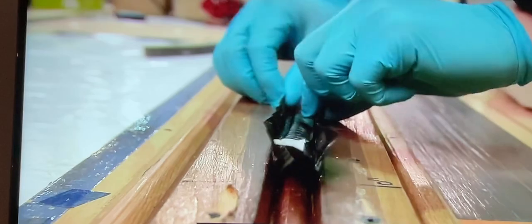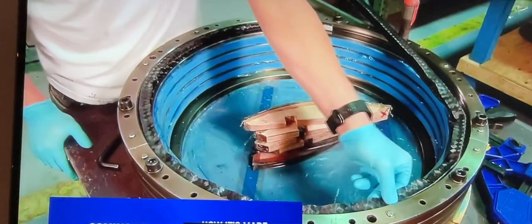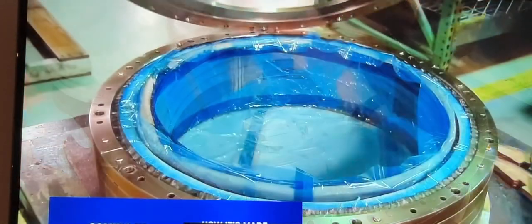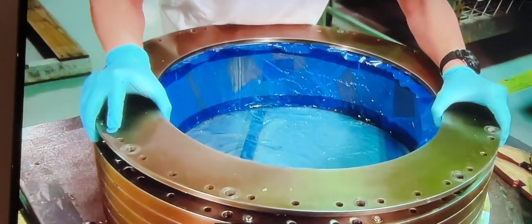Using a kind of wedge, he again puts on the pressure, causing the carbon fiber and film adhesive to stick together. He transfers the long layers to a round mold. As with the sidewalls, he heats the rims under pressure to set the shape. He'll get 5 wheel rims out of this one tool.